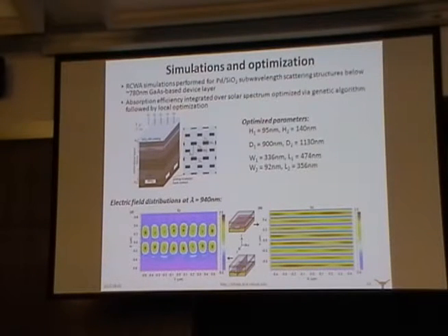And the characteristic feature sizes range from, roughly speaking, about 100 nanometers to, say, roughly 500 nanometers. Okay, so those are the characteristic sizes of the structures that you have to make in order to get this idea to work. And if you have structures like this, then you can get, at certain wavelengths, very efficient coupling into these well-defined guided modes.